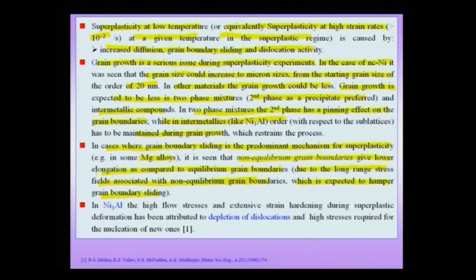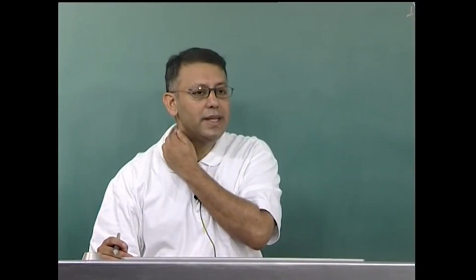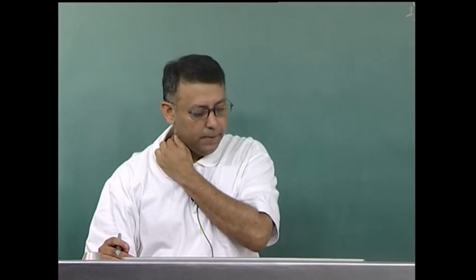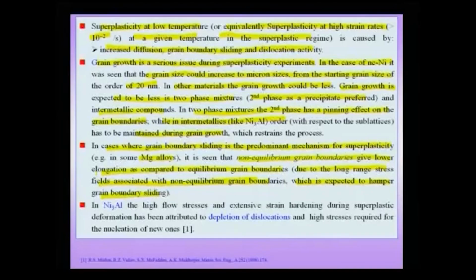sliding. So, this is an issue wherein people have gone into details of the mechanisms of how the grain boundary sliding takes place and what kind of a grain boundary would give you what you call an easy grain sliding versus a difficult sliding, and it is seen that equilibrium grain boundaries would slide easier as compared to the non-equilibrium grain boundaries which are associated with a long range stress field.